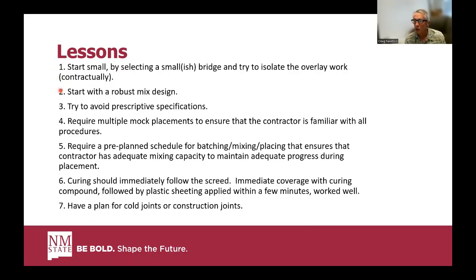Second thing is start with a more robust mix design. We had a very lean mix design. We had really put a lot of work into trying to optimize sustainability and low cost so that we drove our strengths down to just above 17,000 PSI. And then when we enforced Buy America and we had to change our fibers, it required more work than it should have. If I could go back and change something, we would have started with a more robust mix design so that changes like that wouldn't have so much of an effect.